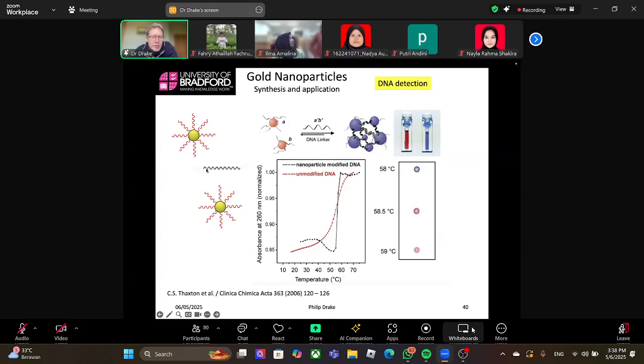If you add in the complementary strand, so this is now the DNA you want to detect. This is a complementary strand. It binds to both of these. So the DNA forms a double helix on one particle, leaving a bit sticking off. This forms a double helix with a second particle, so the particles now become coupled together. When they do that, the color changes. It goes from being red to being blue. So now you've got a sensor that detects this particular strand of DNA, this sequence of DNA. If it's present, you get a blue color. So this is a way of developing the first kind of sensor for DNA.